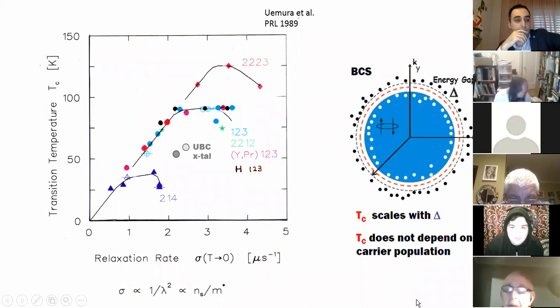And this is different from what you expect in the simple BCS, Bardeen-Cooper-Schrieffer, simple metal superconductors. In the simple metal superconductors, the metals have something called a Fermi sphere, and superconductivity occurs as a result of electron-phonon coupling. Superconductivity occurs because there's something called an energy gap made in the superconducting state around this Fermi sphere. And if you have an energy gap, then there is no dissipation or scattering around. And that is the origin of this special quantum behavior called superconductivity, an electric current without decay or without resistivity. This is all coming from the existence of the energy gap.